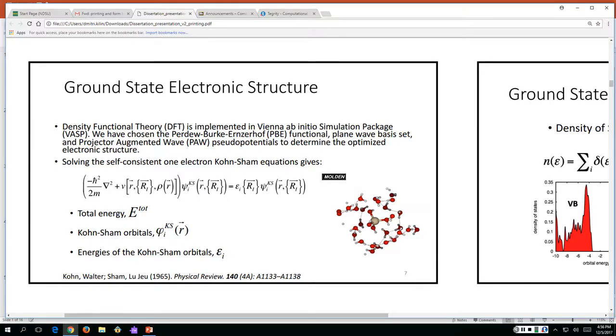0.57 electron volts. And so this newly introduced occupied state is going to give us the potential for low energy absorptions, which is ideal for titanium dioxide, as they primarily have a band gap close to 3.2 electron volts. And it's also going to give us the possibility for new relaxation pathways.